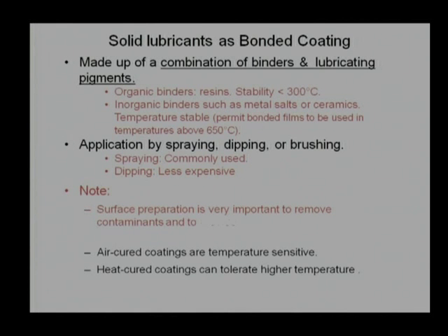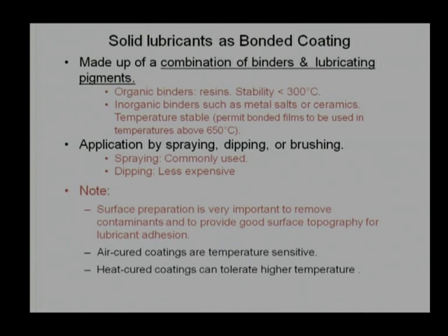Now, a few notes, a few conclusions based on what we have mentioned, can be stated. To apply solid lubricant in coating form, we require a good surface preparation. Some irregularity on the surface will help us deposit the solid lubricant on the surface easily. That's why most often we use emery paper to rub the surface, make a slightly irregular surface, and then apply solid lubricant on the surface. Surface preparation is important.